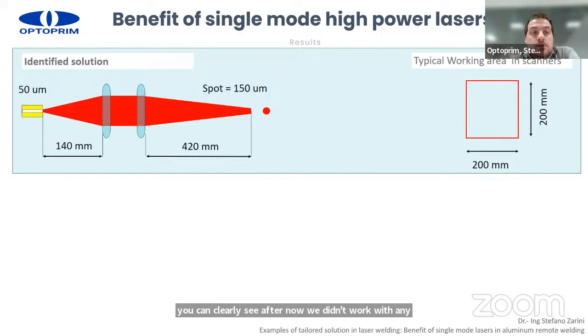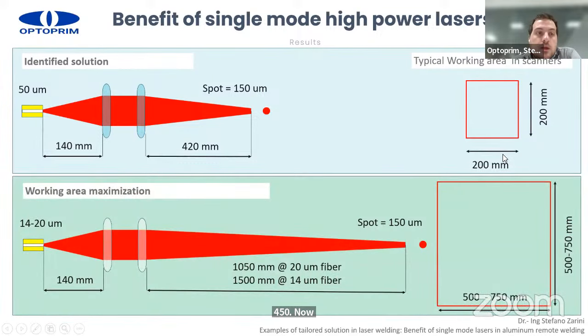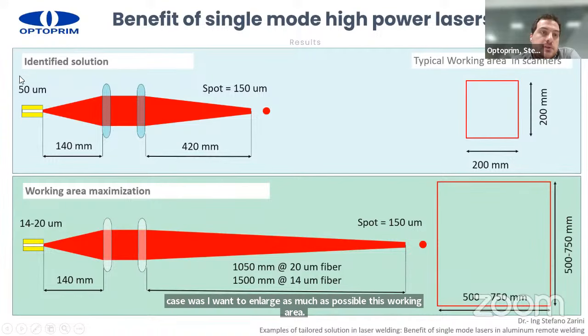So given the identified solutions and given the goal to maximize the working area for laser processes, we worked with this type of configuration, so 50 micron spot, 140 millimeter collimation, and 420 millimeters focus length, obtaining a laser spot of 150 micron. Nevertheless, the request of the customer in this case was, I want to enlarge as much as possible this working area. So squeezing as much as possible the fiber size, so moving to single mode lasers, and now we understand why we decided to limit up to 3 kilowatt, because currently most of the single mode lasers with the highest power can achieve up to 3 kilowatt.